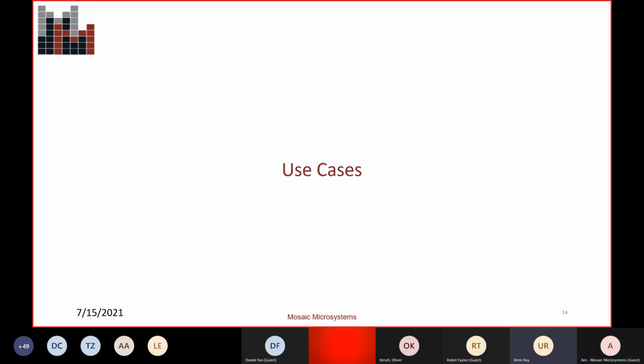From Roger Massey, what's the capability in terms of fully filled TGV diameter and depth? Right now, the most mature capability is a 3-to-1 aspect ratio, so a 30 micron via in a 100 micron thick. But we know that we can make vias 15 micron diameter in a 100 micron thick, and we're also working on, or have demonstrated, a 30 micron via in almost a 200 micron thick. So we know that these can be filled. I don't have as much data for the latter two, but we think 3-to-1 to 6-to-1 aspect ratio is where we're going to be playing.